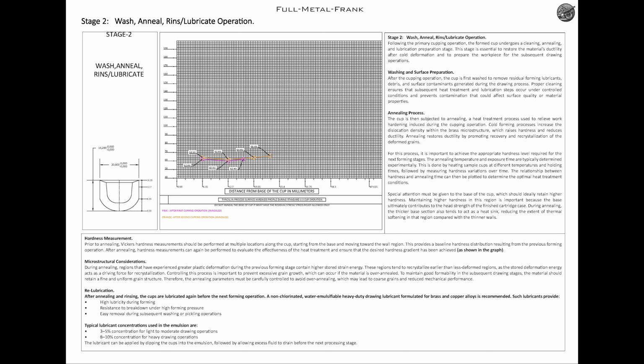Special attention must be given to the base of the cup, which should ideally retain higher hardness. Maintaining higher hardness in this region is important because the base ultimately contributes to the head strength of the finished cartridge case. During annealing, the thicker base section also tends to act as a heat sink, reducing the extent of thermal softening in that region compared with the thinner walls.